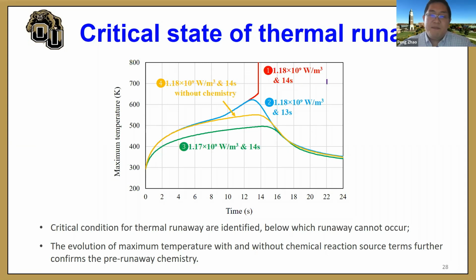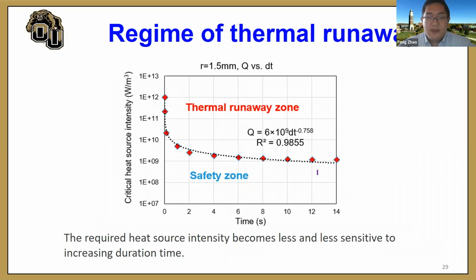It's a critical state including a pair of heat source intensity and duration time that can describe the critical condition for the onset of thermal runaway. So by identifying many different pairs of this critical heat source intensity and duration time, we connect them, we can actually form a regime diagram. This regime diagram basically means for a certain duration time, if your heat source intensity is above a certain threshold value, thermal runaway is going to occur. Otherwise, it's safe. Right? So this is very simple, but it can give a good guidance in terms of the control of batteries.